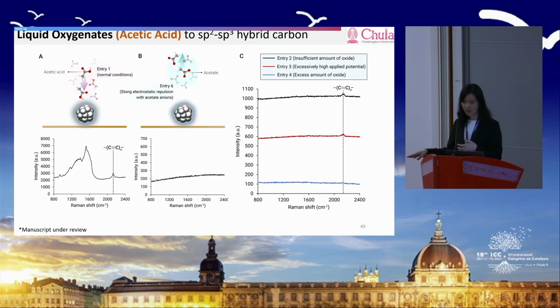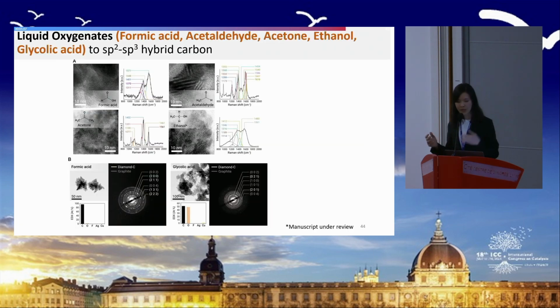towards carbon. Or if we apply too high a potential, what happened? It's going to force the negative bias of the metal nanoparticles under this nanocrystalline system. That also worsens it, with no reaction towards the carbon. If we have an insufficient amount of oxides, we also didn't make it all the way to the sp2, sp3 carbon. We see some linear acetylenic carbons as well. And yes, this worked with acetic acid, and it worked with other types of liquid oxygenates.